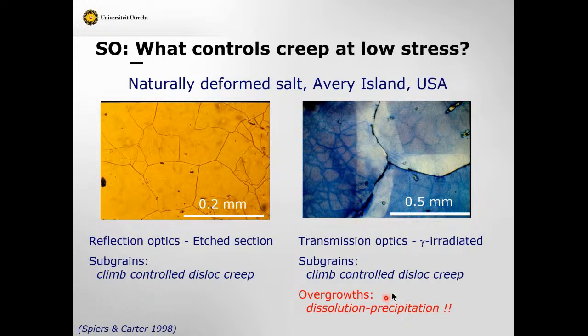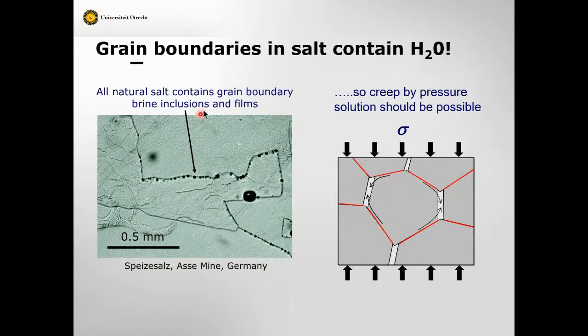And what you're seeing here then is not only evidence for dislocation creep with climb control and subgrains, you're seeing overgrowth. It's evidence for dissolution and reprecipitation in the form of crystal growth. So something is going on here with dissolution and reprecipitation. And that is really not that surprising, at least I felt not. But